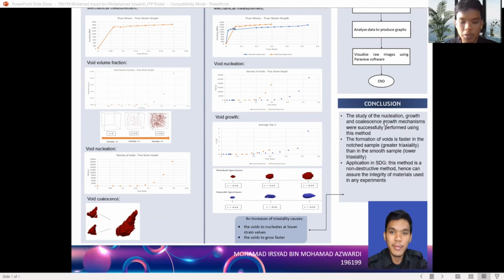Right. So as a conclusion, the study of the nucleation, growth and coalescence mechanisms was successfully performed using this method. The formation of voids is faster in the notch sample than in the smooth sample. And an increase of triaxiality causes the voids to nucleate at lower strain values and to grow faster. And the application is in SDG.